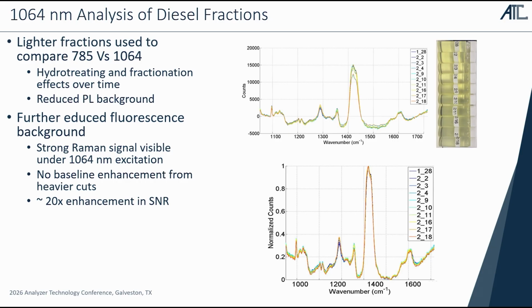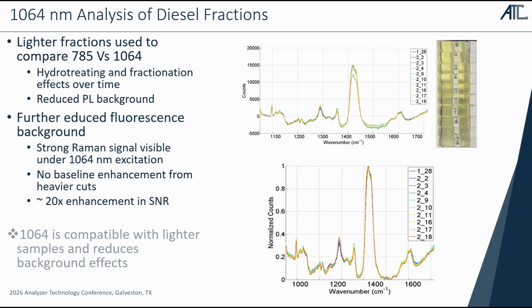And so when we analyze it using our new Raman configuration, you can see that there's a further reduction in the baseline intensity. There's only about a 20x enhancement in the signal to noise compared to the heavier diesel fraction, or to the heavier gas oil samples. But this essentially is just telling us that, yes, we can access these samples that are also usable in 785, and then we can also do samples that are completely inaccessible with 785 as well. And so it's also compatible with lighter fractions in that way too.